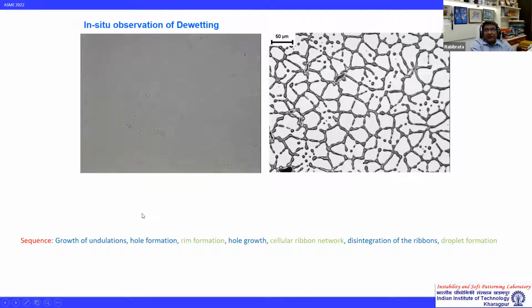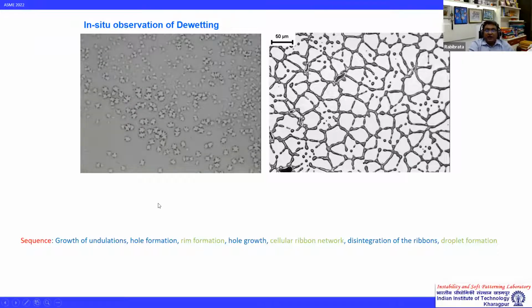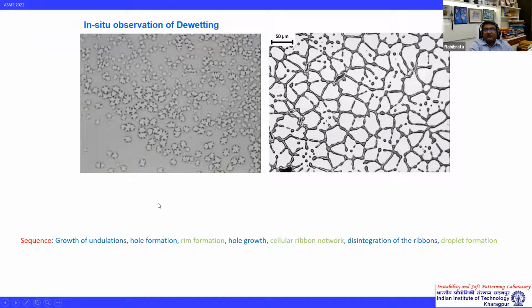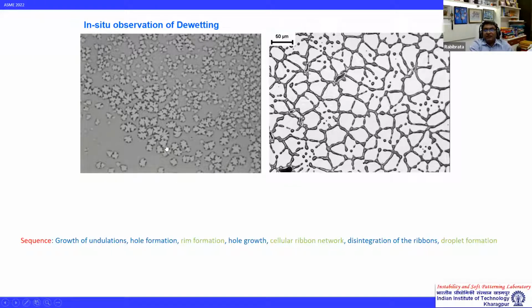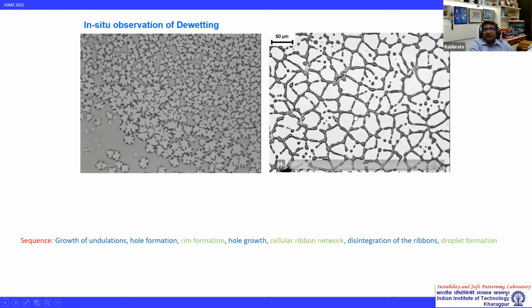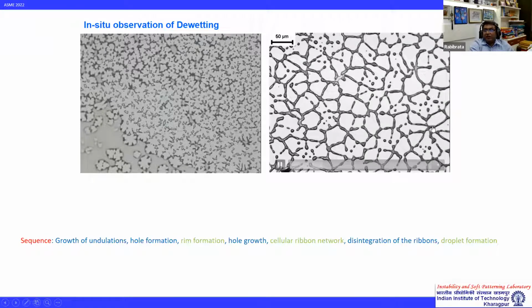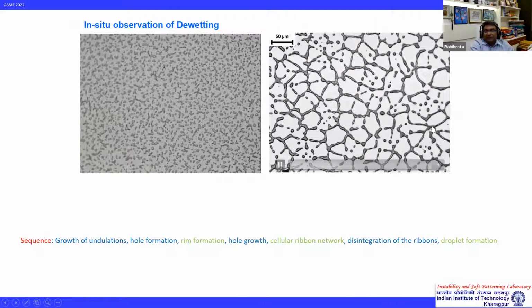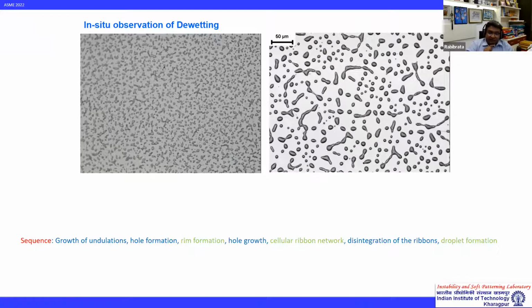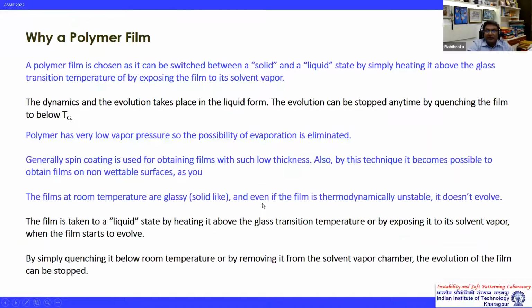So all you have taken is a spin-coated ultra-thin film of a polymer, which is in a liquid form, and you just heat it above the glass transition temperature, and you see the film completely ruptures eventually into isolated droplets. So this is the physics of spontaneous instability in an unstable film, but remember, this manifests only in a liquid film. So what are the necessary criteria for a film to become unstable?